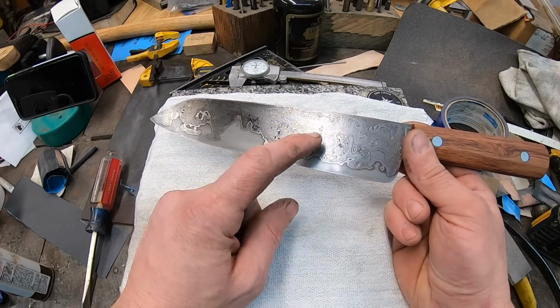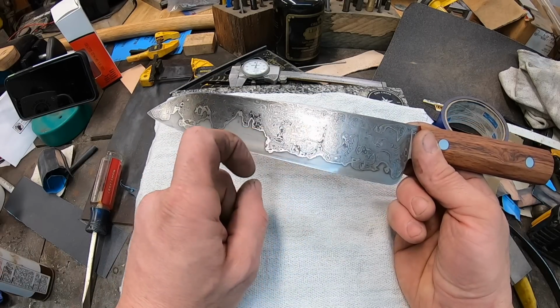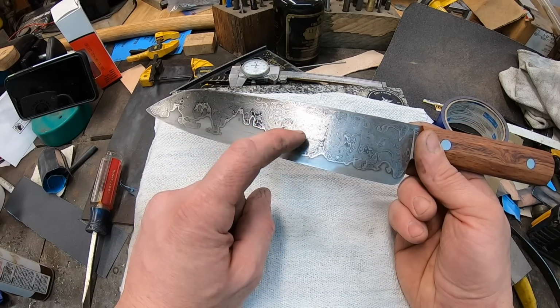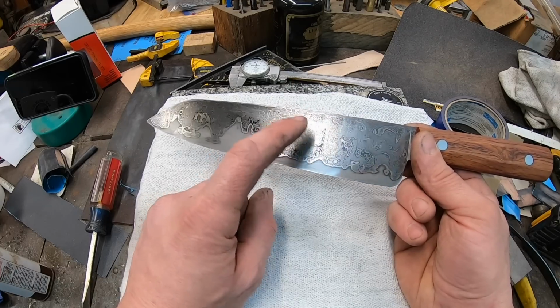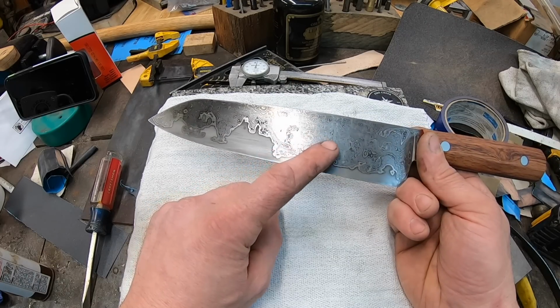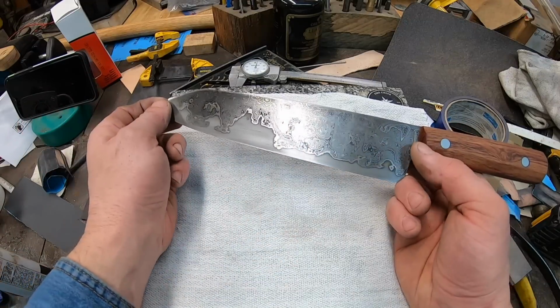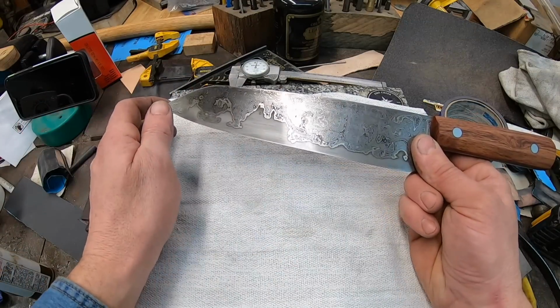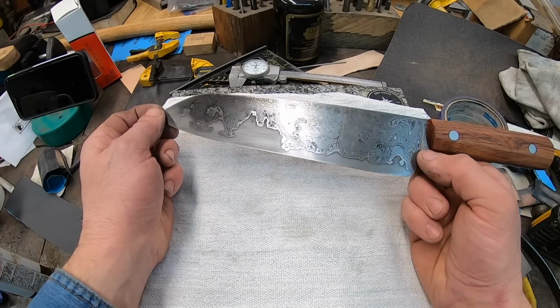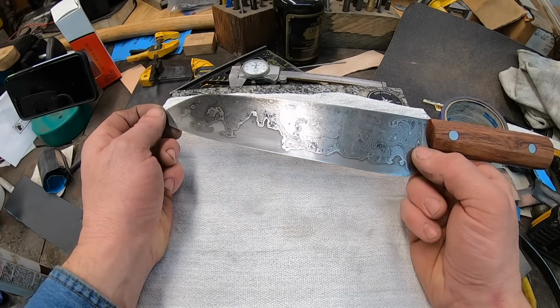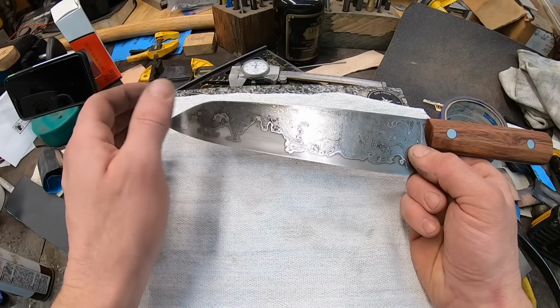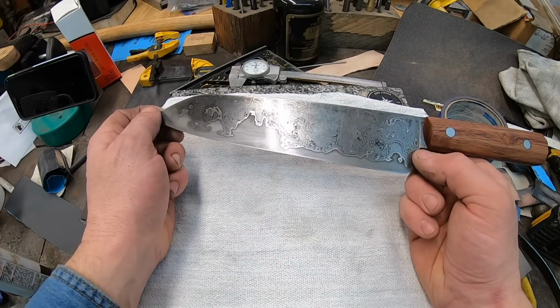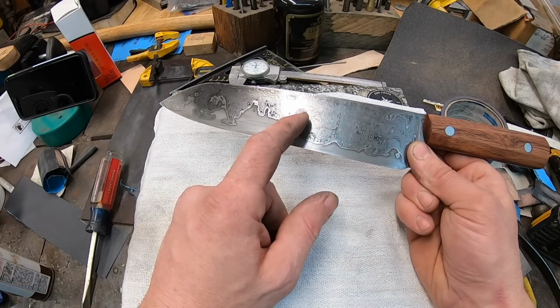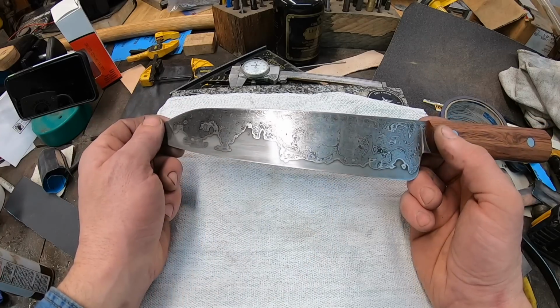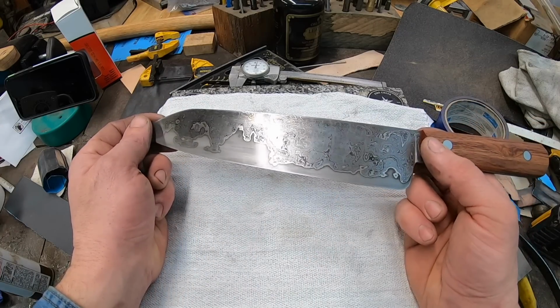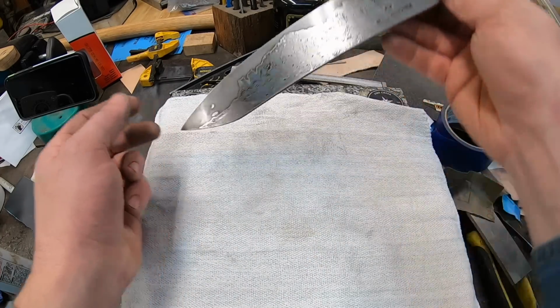Now, when it comes to the pattern, I think the main thing that happened was just a lot of hammering, and I should not have folded my cladding steel as many times and left it a lower count pattern, and I think we would have been okay. But when you get up into the higher or the finer patterns with the higher layer counts, it's often susceptible to a lot of hammering, and you can really just kind of meld those layers together. And then when you go to etch it, it's somewhat less than what you expected. And so that's kind of what happened there, to my knowledge.